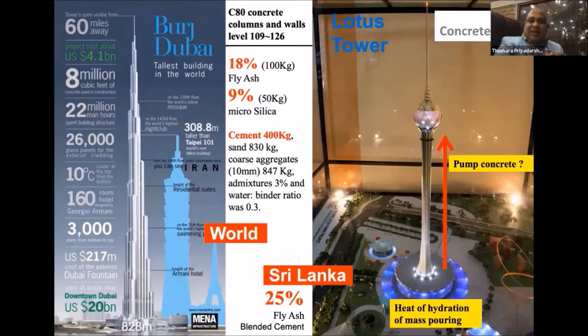So second, you have to take care of the heat of hydration. How you manage heat of hydration is mass pouring, especially in the pile cap area, and even bigger retaining walls and all others. So heat of hydration needs to be managed. Then in the main columns and all others, strength matters. So how do you select your material to match all these? It is by using our knowledge of engineering. So for Lotus Tower, I can remember they used 25% fly ash blended cement for most of the applications in general because it's really good for heat of hydration. You can get the required strength, and it is really good for pumpability.